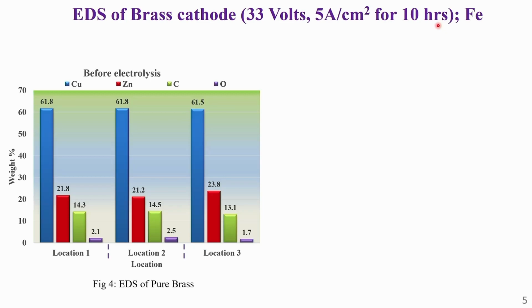Let us look at transmutation results of brass alloy. Electrolysis of 1 molar aqueous potassium carbonate is run at 33 volts, 5 ampere per centimeter square current density for 10 hours. Figure 4 provides the original composition of the brass, which is copper and zinc. Blue bar refers to copper and red bar presents the elemental composition of zinc,